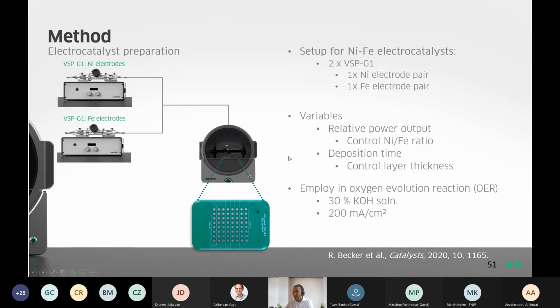We could also vary the layer thickness just by varying the deposition time that we used to get the nanoparticles onto each of these electrodes. And the test reaction that was used was the oxygen evolution reaction, and this was done at relatively high current densities.